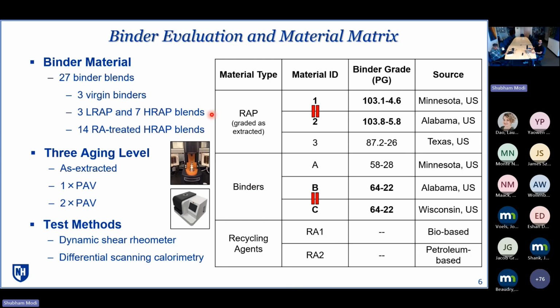With these combinations, we generated 27 binder blends, which included 3 virgin binders, 3 low RAP, 7 high RAP blends, and 14 RA-treated high RAP blends.